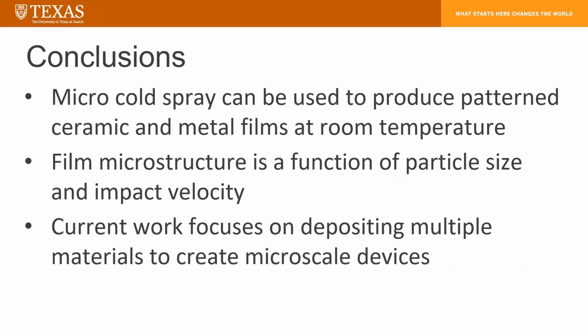The conclusions we can come to are that micro cold spray can be used to produce patterned ceramic and metal films at room temperature. And these work at a variety of input processes and output substrates, so it's quite versatile. The film microstructure is a function of particle size and of impact velocity, and our current work focuses on depositing multiple materials to create microscale devices.